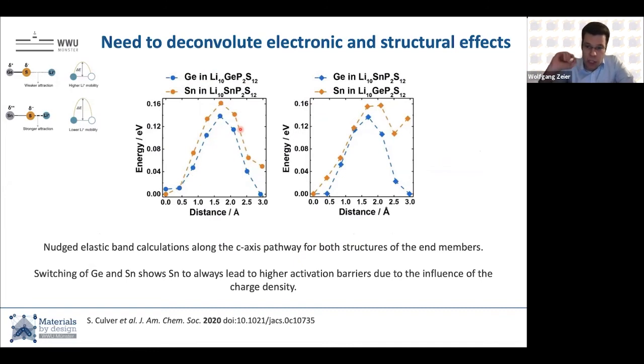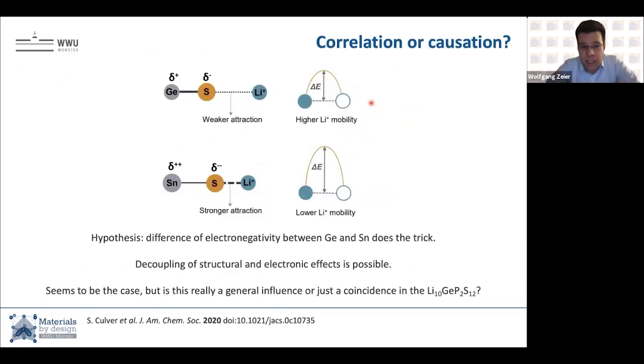Now we decided to keep the structure fixed and swap germanium with tin. So now germanium is in the tin structure in blue and tin is in the germanium structure in orange. And even though these are the unrelaxed structures of the initial starting materials, tin again has a higher activation barrier. And so I think this does show that switching germanium for tin leads to the higher activation barriers due to the changes in this electronic charge density, and the idea of this change of electronegativity seems to really do the trick. So it seems like we can decouple structural and electronic effects.